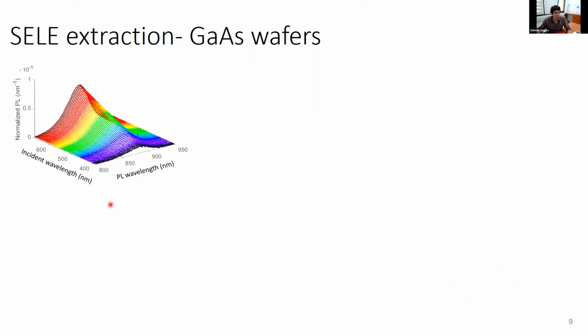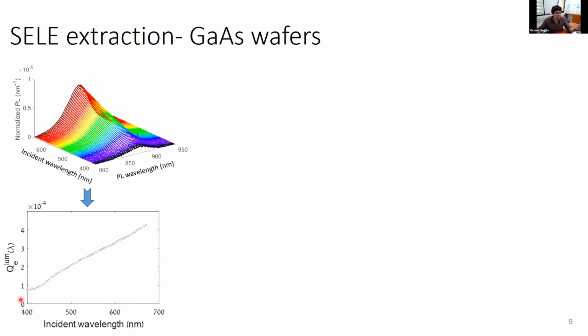The output that we get, this is pretty much the raw data. These are photoluminescence spectra as a function of different incident wavelengths. It is already calibrated here, so by integrating each of the spectra, we can get the photoluminescence quantum yield, which changes with respect to the incident wavelength. And now all that is left is to plug all these and the optical generation profile into this equation and extract the spatial external luminescence efficiency. Before we do this, let's take half a minute to think about what we expect to see.